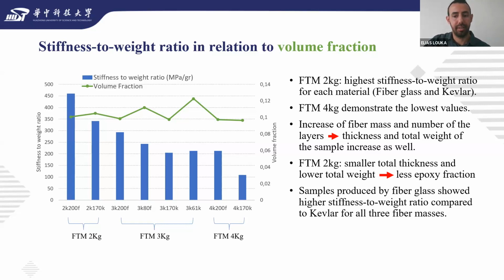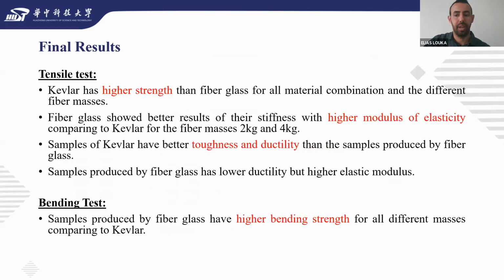The tensile test showed that Kevlar has higher strength than fiberglass for all material combinations and for all different fiber masses. Fiberglass showed better results in terms of stiffness, with a higher modulus of elasticity compared to Kevlar for the fiber masses 2 and 4 kilo. It can also be observed that samples of Kevlar have better toughness and ductility than the samples produced by fiberglass. On the other hand, samples produced by fiberglass have lower ductility but higher elastic modulus.